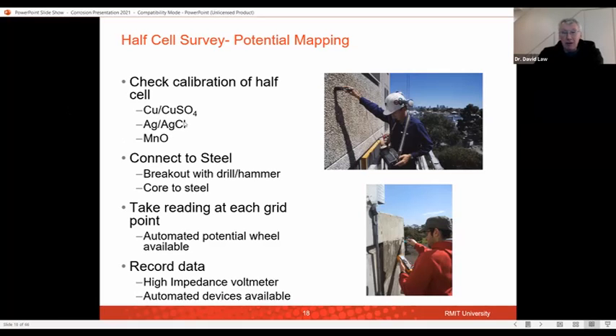If we want to monitor this over a long period, though, we may well want to actually install an electrode in the concrete and see what's going to happen over a number of years, perhaps 20, 30 years even. And for this, we can use things like silver chloride or manganese oxide electrodes that are more stable and will last longer if we put them inside our concrete, whereas our copper sulfate will not last that long because it will dry out if we try to install it inside our concrete.